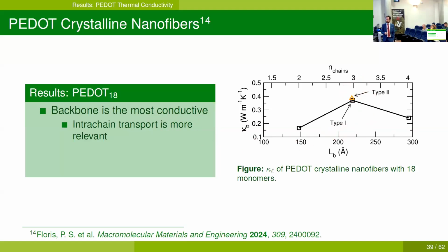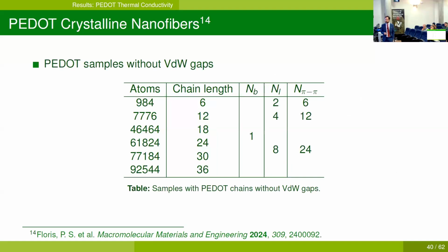And in the case of PEDOT chains made of 18 monomers, the backbone appears to be now more conductive, since we are here at 0.4, which means that intrachain transport becomes more relevant for this chain length. Similar things can also be said for lamellar and pi-pi direction, as the previous cases of 6 and 12 monomer chains. Now moving to the PEDOT samples that do not include van der Waals gaps along the backbone, we created them with chain lengths of PEDOT ranging from 6 to 36. So there is only one repetition along the backbone, and increasing numbers for lamellar and pi-pi.